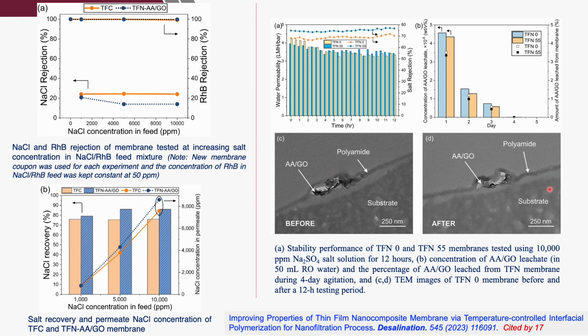And for the FESEM and TEM analysis, you can see here the stability of our membrane containing the graphene oxide before and after the filtration for up to 12 hours. And you can see here that graphene oxide actually is still embedded within the polyamide layer, and there is no leaching of the graphene oxide from the polyamide layers.